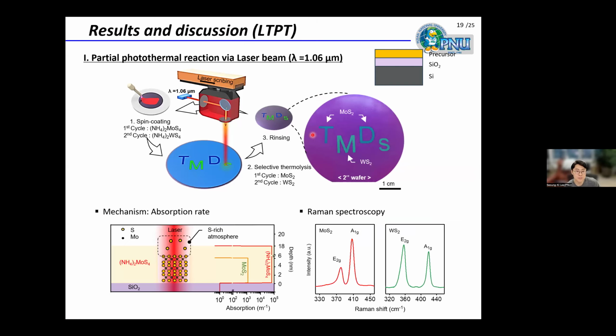The process is simple, but the key factor is the selection of the laser. When we use the fiber laser in this system, we can avoid damaging MoS2 due to the significant difference in absorption between the precursor and MoS2. As shown here, the absorption differs by about 3 orders of magnitude. Therefore, the fiber laser efficiently hits the precursor layer. However, once the precursor is thermally converted into MoS2, further heating is suppressed because the laser light passes through the MoS2 material due to its low absorption.